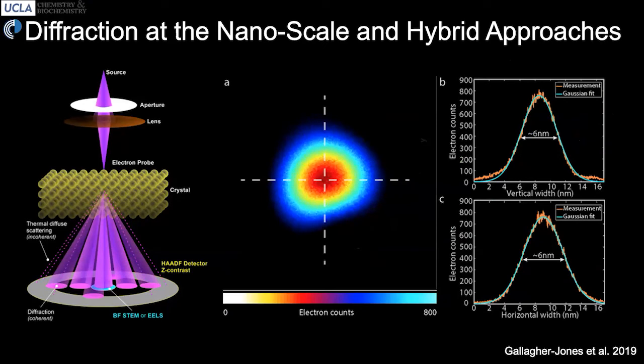Now, in cases where there are samples that are even a challenge for conventional electron diffraction, we're really excited to try to push the limits of the technique at the moment. And rather than illuminating a micron size area or even larger, we're trying to change the illumination area to scale it down to the size of just a few repeat units within a crystal. And so we've partnered with folks at Berkeley Lab and are trying to set up the very same approaches here at UCLA to try to make pencil beams, or beams that are highly parallel but very small in diameter.